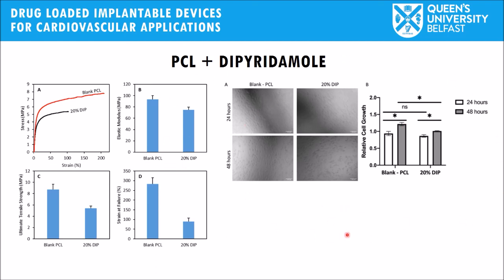Finally, we tested the compatibility with cells on the surface of the materials, and we can see that the cells proliferate, and there was not a big difference in cell growth when we compare with blank grafts. So the presence of the drug is not going to prevent the proliferation of cells on the surface of the material. That shows that these materials can be promising as scaffolds to regenerate vascular tissue.